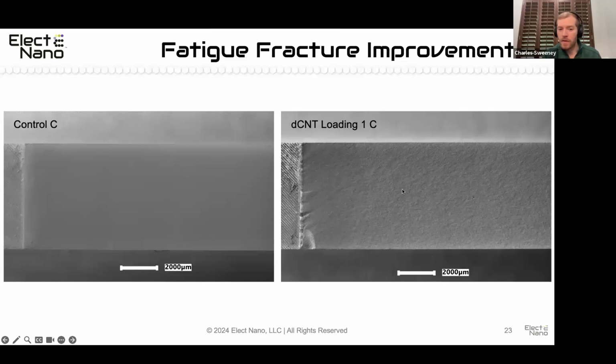But even then, the surface roughness of the nanotube reinforced system is dramatically higher. And that's always a good sign when you're looking for a ductile versus brittle failure: how rough is the surface roughness morphology of that fracture surface.